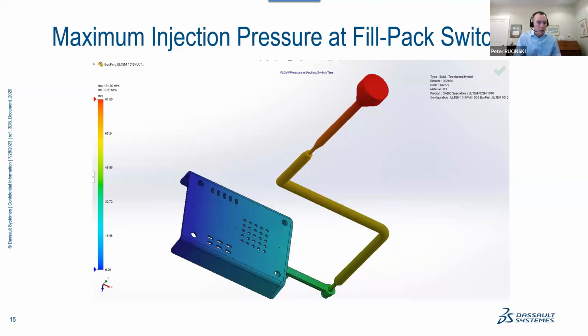the injection pressure requirements and the injection pressure distributions and the pressure drop through the system, as the melt flows through the nozzle of the injection molding machine, in this case through the hot runner system, through the cold runner system, through the gate and into the mold cavity. If you can accurately predict pressures, you can get almost everything else right. And by everything else, I mean shear stress, volumetric shrinkage, and then maybe ultimately molded part warpage.